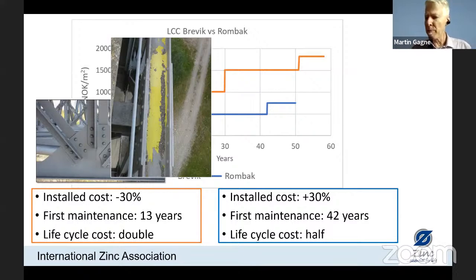A final point I wanted to mention, Graham had talked about paint outperforming zinc in neutral salt spray testing, and this is true. We saw the development of the coating on zinc. When it's exposed to air, we get oxides, hydroxides, and carbonates forming. It's a very complex surface chemistry on the zinc, but that gives it the corrosion protection.